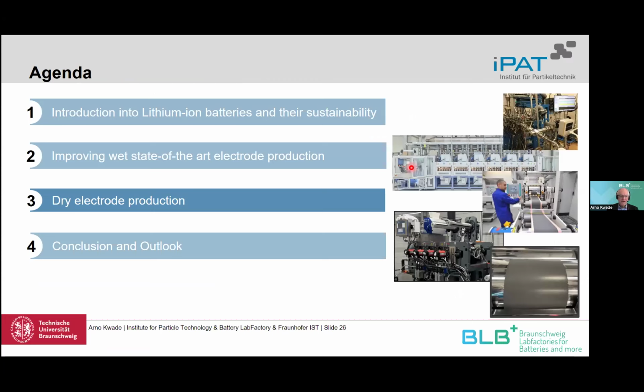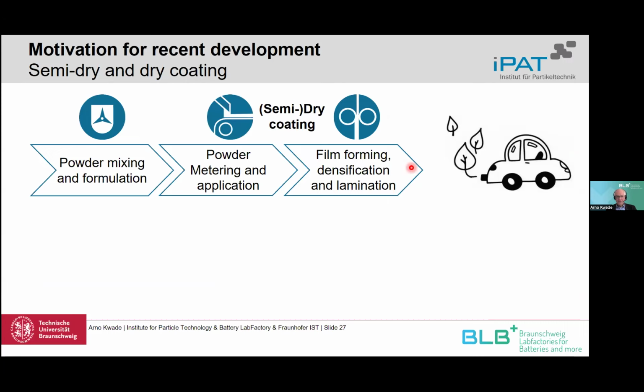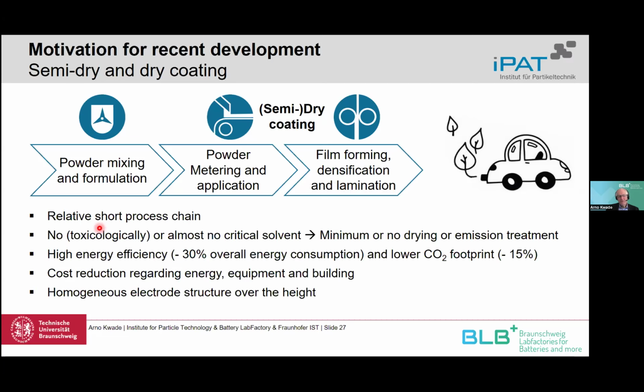It is about dry electrode production. As I said, we have to go for a more sustainable production of electrodes. One possibility is to change from wet to dry coating, or we also call it semi-dry. I will show you how that works. This also shortens the process chain. So we have a more or less dry mixing, then the dosing of the powder and the film formation, and no drying and no calendering, because the film formation is, you will see later, at the same time the calendering process. So we have a relatively short process chain.